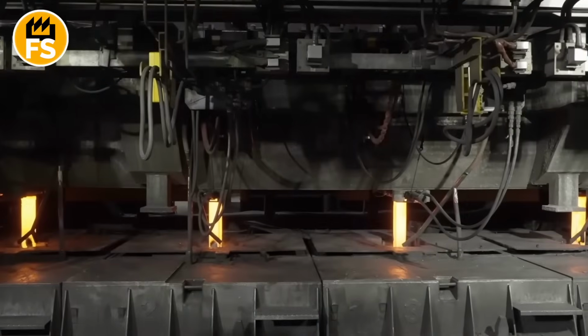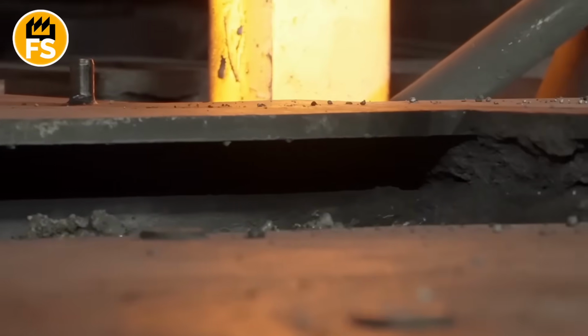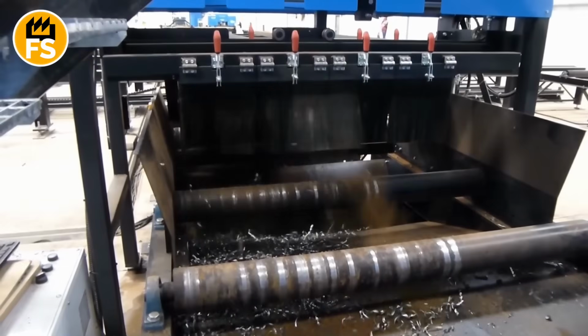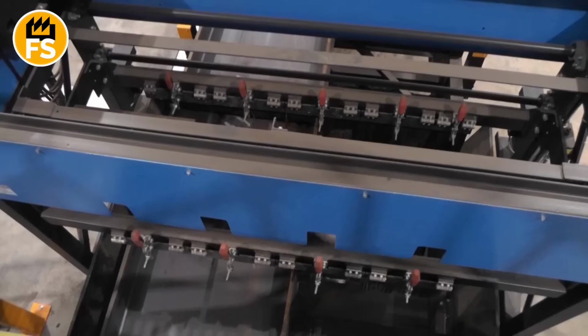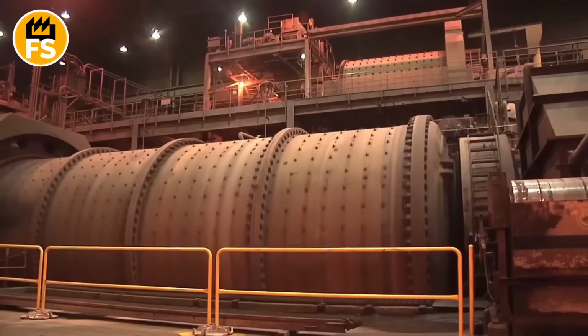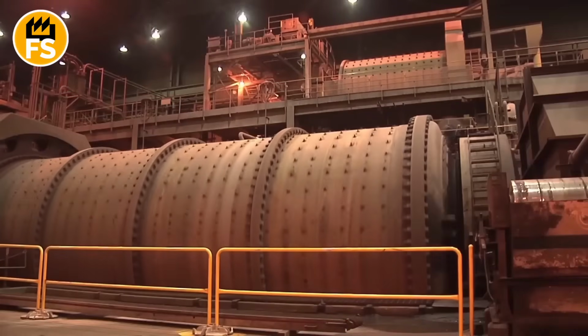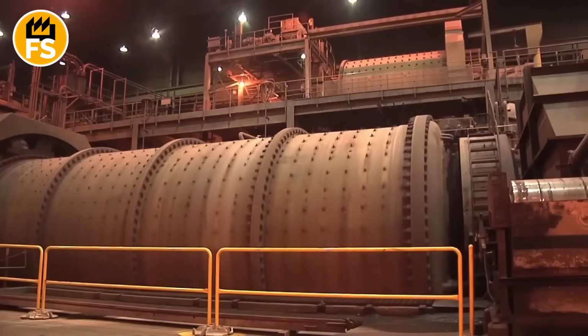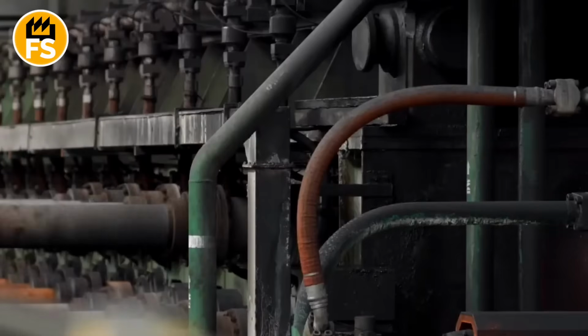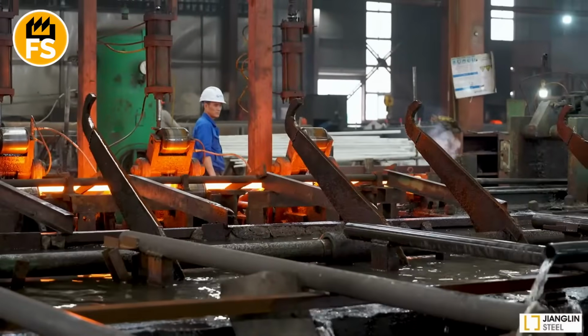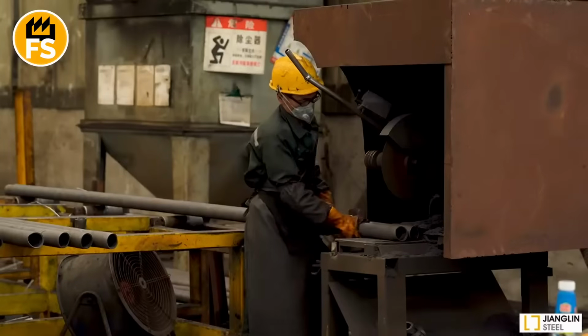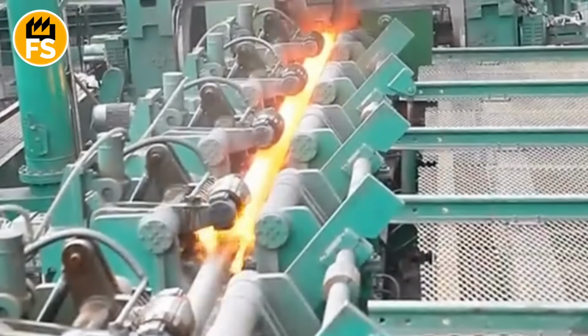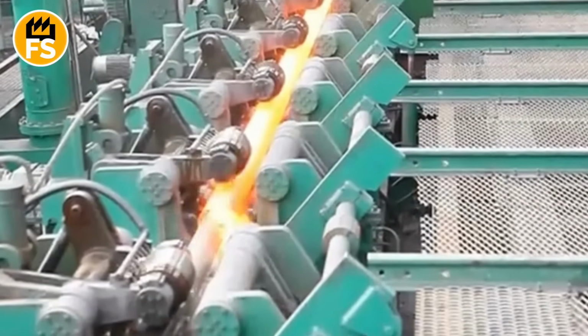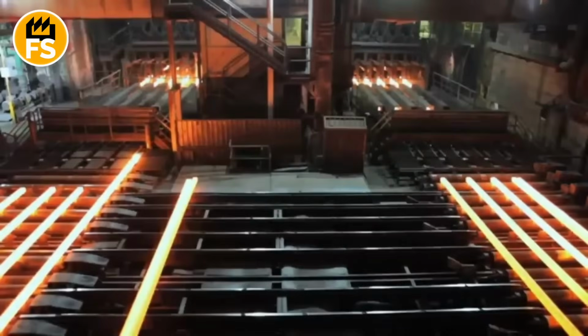Next, the monster drill comes into play. It weighs 12 tons. That's like 2 elephants. The red-hot steel billets, massive cylinders, are removed from the furnace and delivered to a special rolling machine, where one of the most crucial stages of seamless pipe production begins, creating the hole inside. The piercing process looks impressive. The red-hot billet is placed on a special support ring in front of the piercing mill, where a thick, cone-shaped rod awaits it, the so-called piercer point or piercing mandrel.